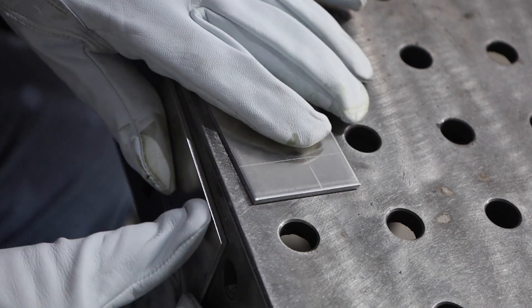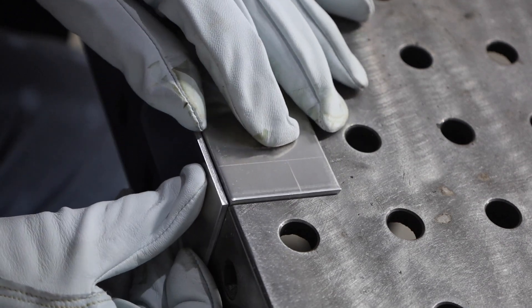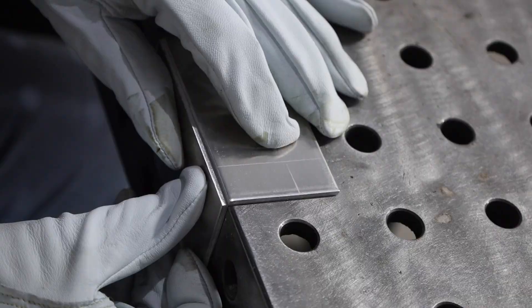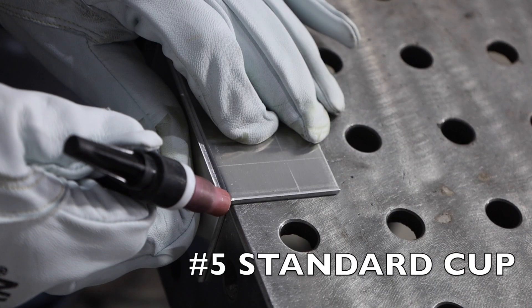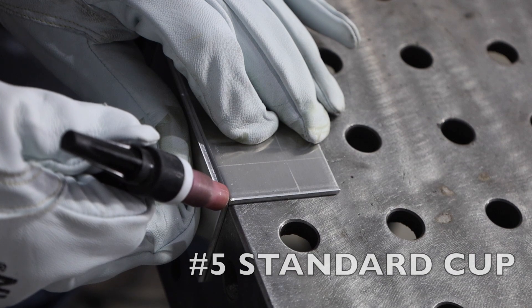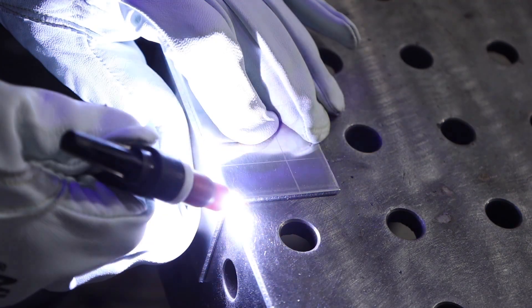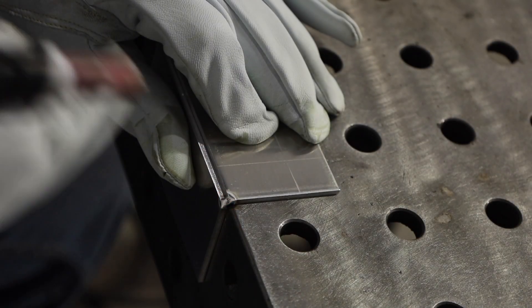Now, in order to tack aluminum together, I'm just placing it on the outside corner of my weld table, you could do this on a scrap piece of square material or angle iron. Once those are held in place, I'll get my tungsten in there with a nice arc length, and then I'll start off at a lower amperage, and then as soon as I see some metal starting to form a puddle, I'll just floor it and give it full amperage and let off, and that usually works pretty well for me to get an aluminum tack without using filler.